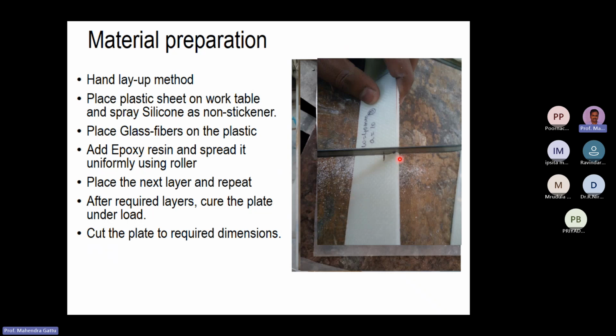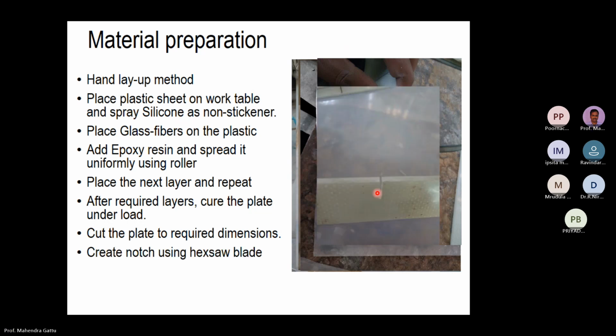So here we see a picture of the test specimen, and we are introducing a notch here. Notch is a crack. This is a blunt notch because the width of the blade is very large. So we used a blunt notch, but later we realized that we should use a very sharp notch. Initially, we used a blunt notch crack, and we did our experiments on this. So this is a glass fiber specimen, and this is the crack which we have created in the glass fiber here.